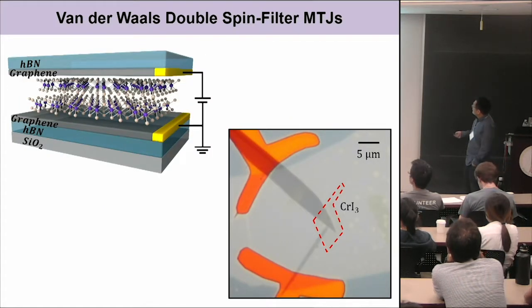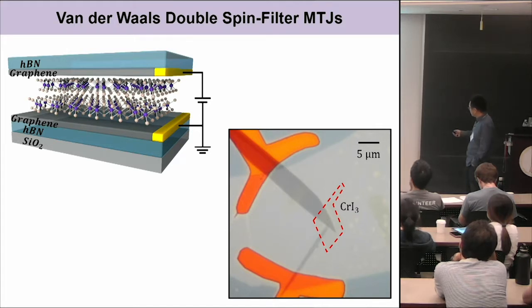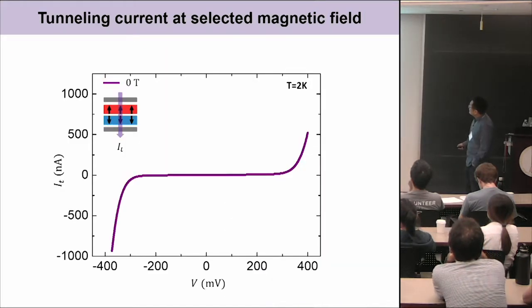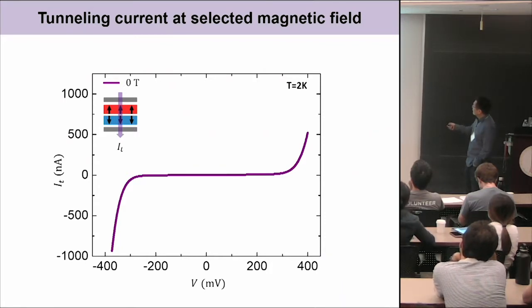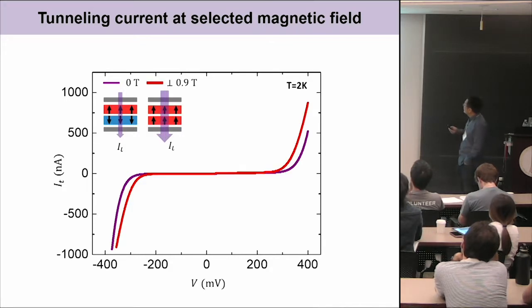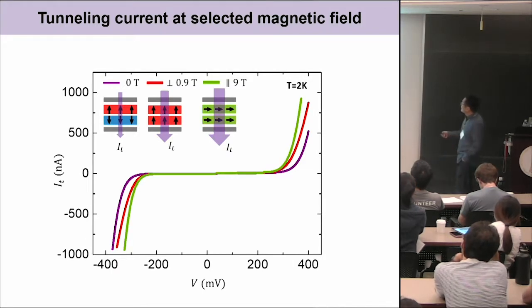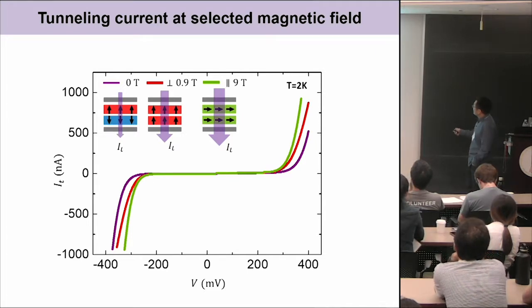Here's a device image. We have graphene on top and bottom as contacts, and we have a bilayer CrI3 in the middle as a tunnel barrier. Here's just an optical image of the device. First we measure the tunneling current as a function of applied bias at 0 Tesla. Then I increase the magnetic field to align the spins in the vertical direction. Now you can see the red curve, right? The current is stronger than the purple one. You can also align the spins in the horizontal direction. The tunneling current is even a little stronger.